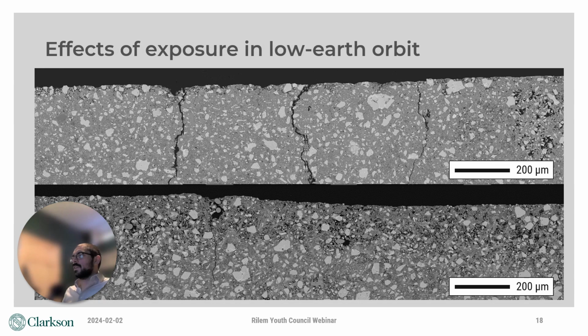The weathering conditions on the moon are another critical challenge. Without an ozone layer, lunar structures experience much stronger solar radiation than Earth structures. They'll also experience significant temperature fluctuations and constant abrasion by lunar dust and microasteroids. We need to know that they'll hold up to these aggressive conditions, so NASA and our partners at Penn State sent some lunar concrete samples to the space station and put them outside in a special platform where they were exposed to the low Earth orbit for about 6 months.